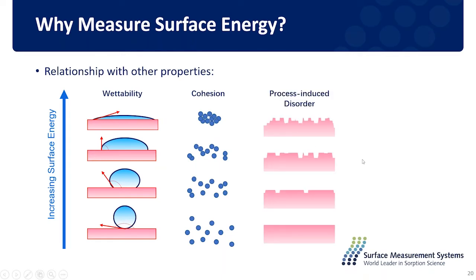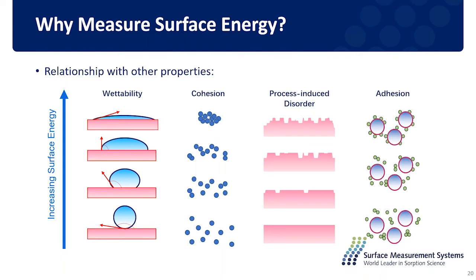And if we are creating more defect sites on the surface, of course, the surface energy will increase, as well as the distribution, the heterogeneity on the surface will increase as well. And if we start formulating different components in a multi-component system, the surface energy is quite important to predict whether the filler or the coating and the base material have a good affinity between each other.